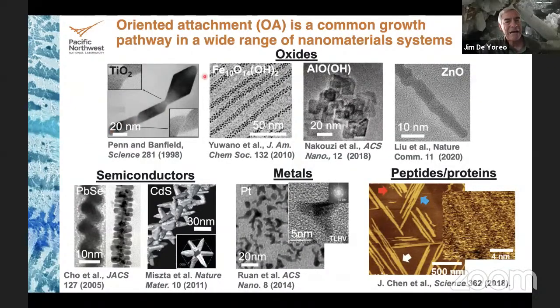They reported TiO2 chains where all the particles were attached on the same kinds of faces and the particles are co-aligned. Here's an example of iron oxides, aluminum oxyhydroxides, and zinc oxide, a very common semiconductor oxide, which grows by oriented attachment. You can see it's made up of these domains, but they're co-aligned along the 001 axis of this wire.